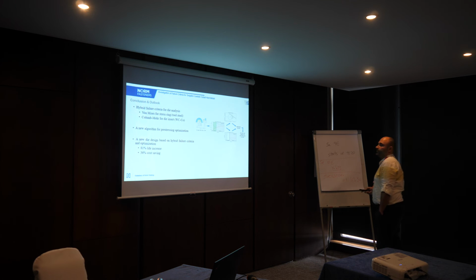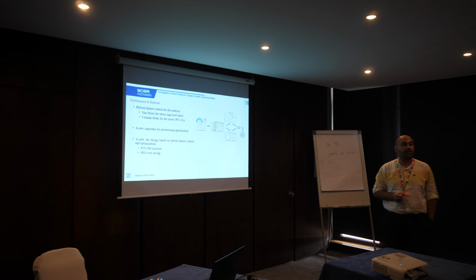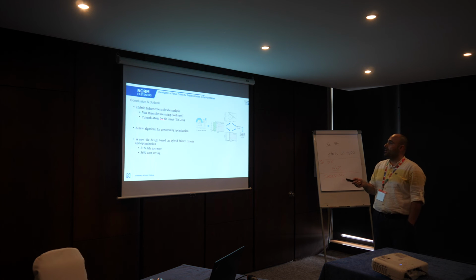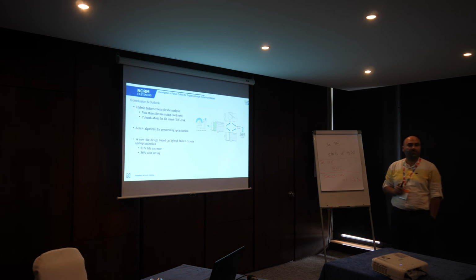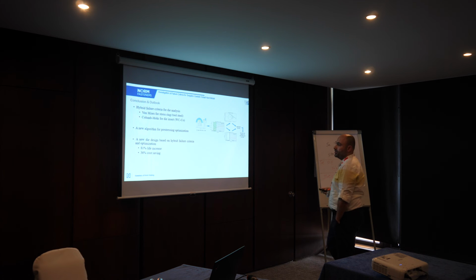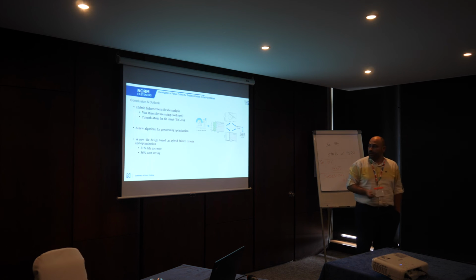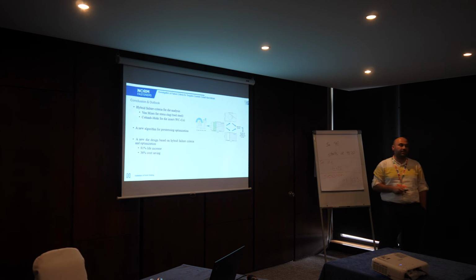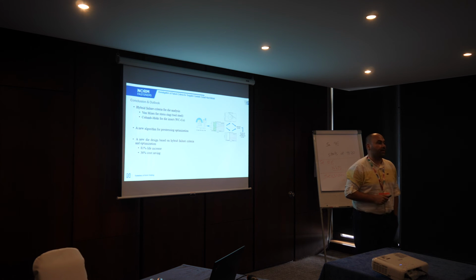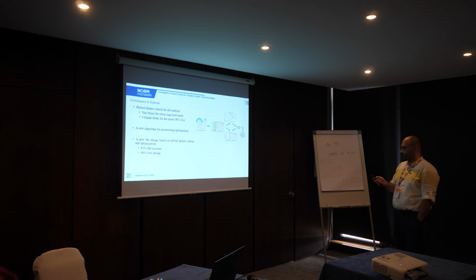So to conclude, we obtained a hybrid failure criteria. We apply the hybrid failure criteria for our dies that we are using in cold forging. And we also produced a new algorithm for pre-stressing optimization. And at the end of the day, we achieved a significant life increase, and on the other hand, with the cost saving, I end up with this application.